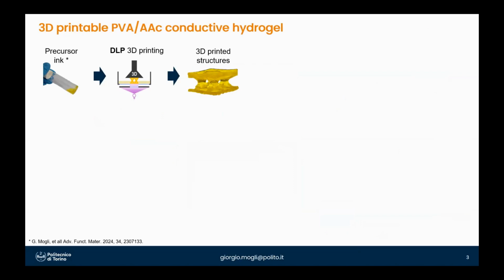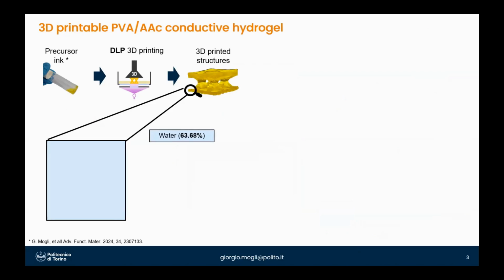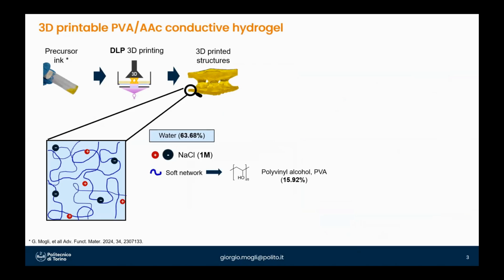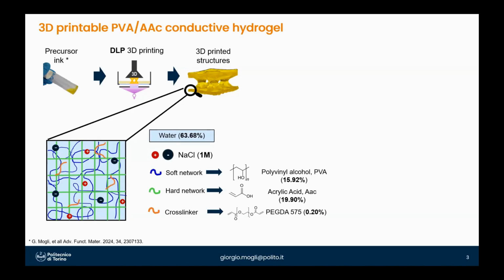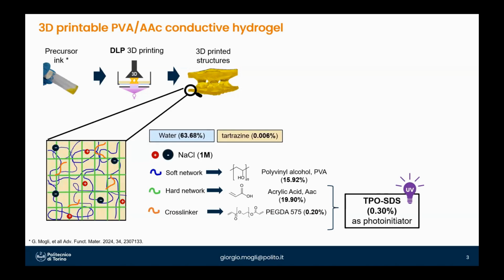that could be 3D printed through the digital light processing technique. The hydrogel is composed of water, in which ionic conductivity is achieved through the dissolution of sodium chloride. The hydrogel is composed of a soft network based on polyvinyl alcohol, interpenetrated with a hard network of acrylic acid, which is cross-linked by polyethylene glycol diacrylate. The two acrylate species react to UV light, and so 3D printing was possible. And so a water-soluble photoinitiator was dissolved into the precursor formulation. The yellow color is given by a water-soluble dye, tartrazine, which was added to improve the resolution of the printing.